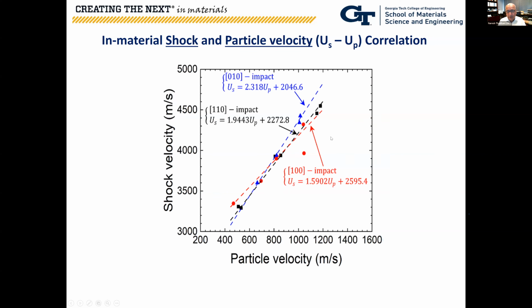So what do we infer from this? Is there an effect of orientation? I'm not showing you the error bars. Without them, it seems like maybe there's a slight effect of orientation. But if you put in the error bars, there would practically be no effect. I think in general, there is not much influence, even though we observe the voids were aligned more along the print direction.